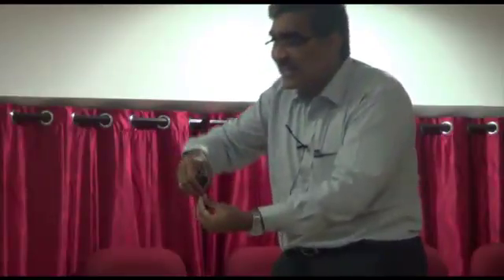So now, these walls, we realized, were actually nothing but... Later we realized that we thought it was just a strain relaxation wall. Then we realized it was actually those screw dislocations I talked about. Those screw dislocations are threading like this and becoming a dislocation inside the film. Now what we are doing by the kinetics, we are actually opening it up. So these are called open screw dislocations of these materials.